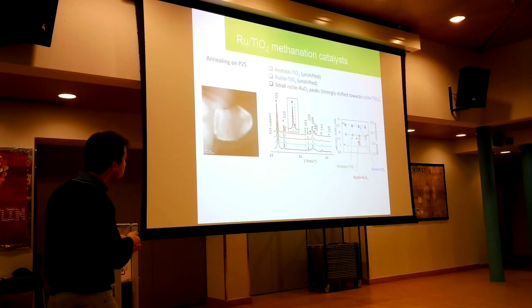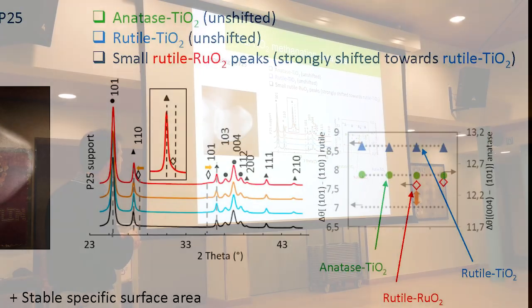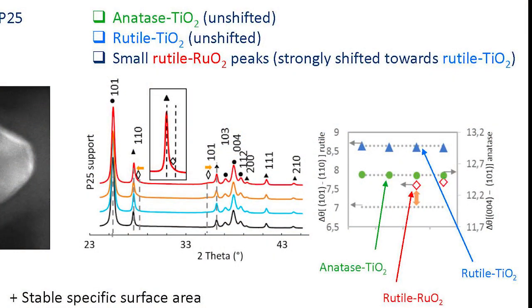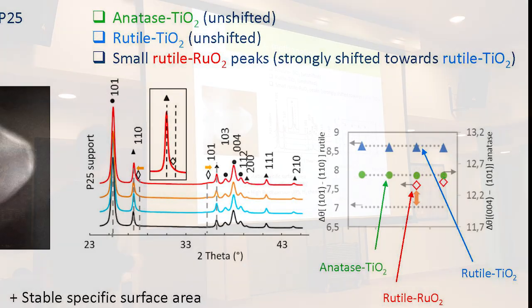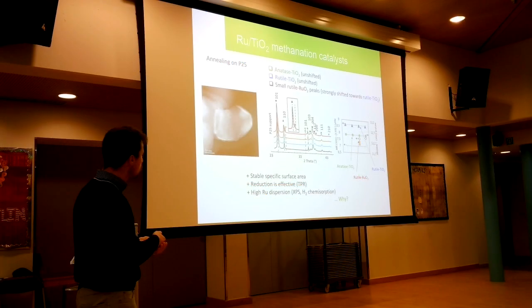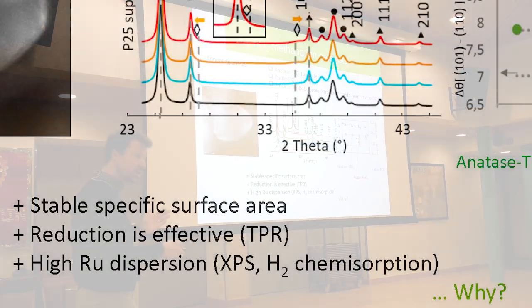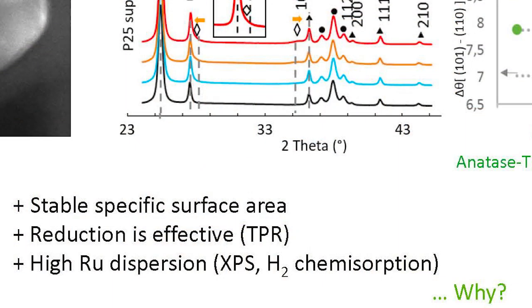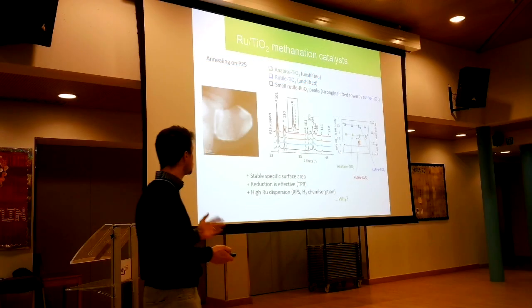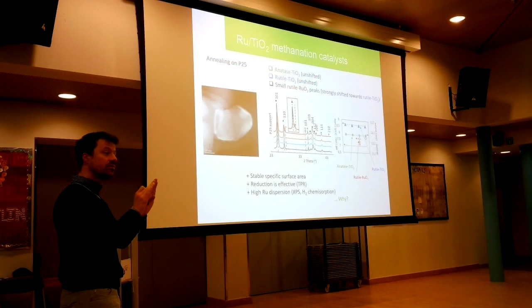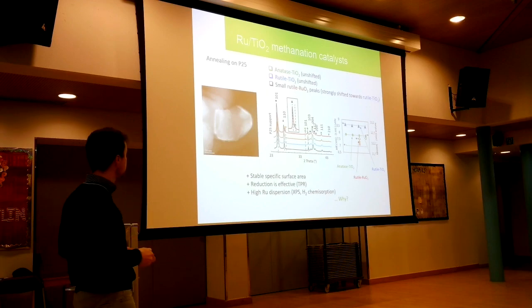But as soon as we increase the temperature here, we see the diamonds for ruthenia strongly shifted towards rutile. In this case, no drop of specific surface area. Reduction is okay, and also the dispersion, calculated by different techniques, is okay too. So we don't have this phenomenon of sandwiching, or trapping in this case.